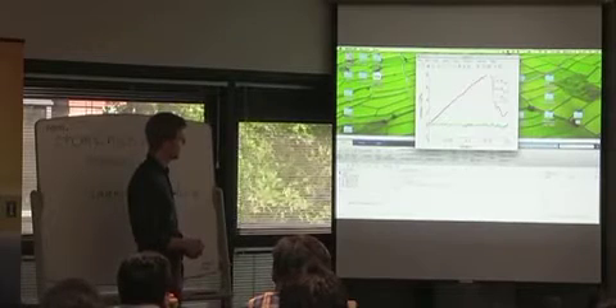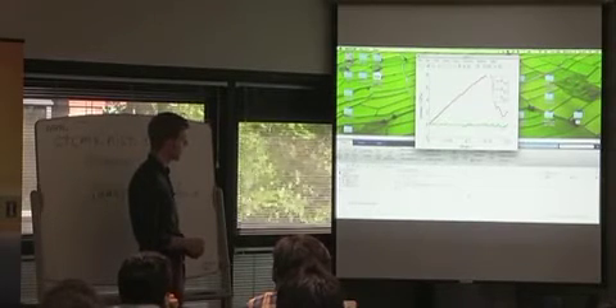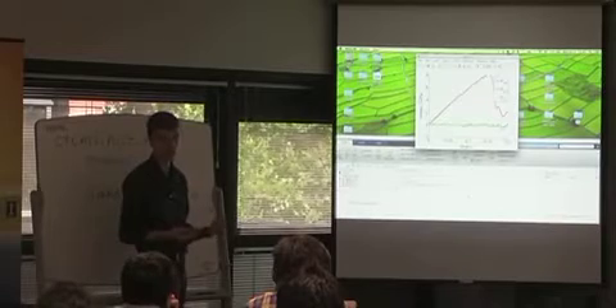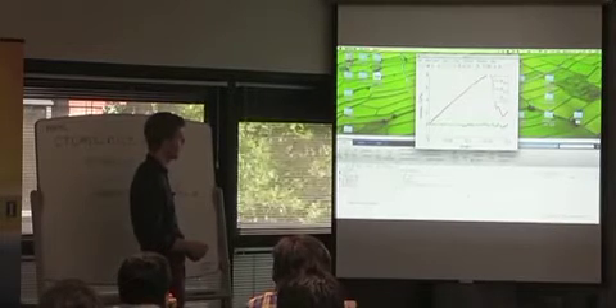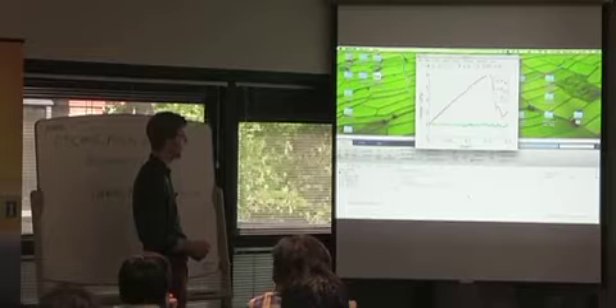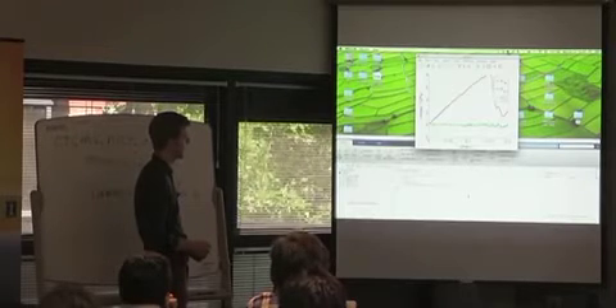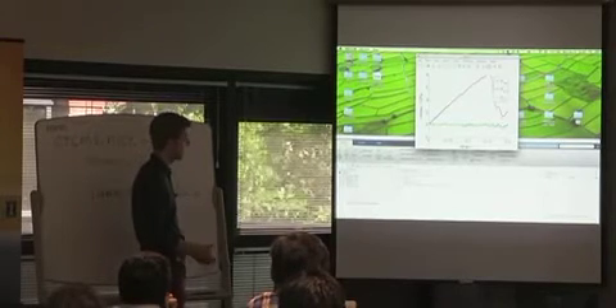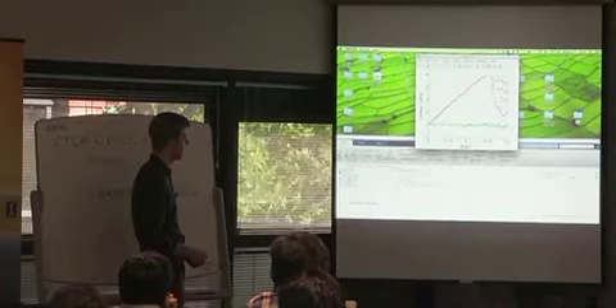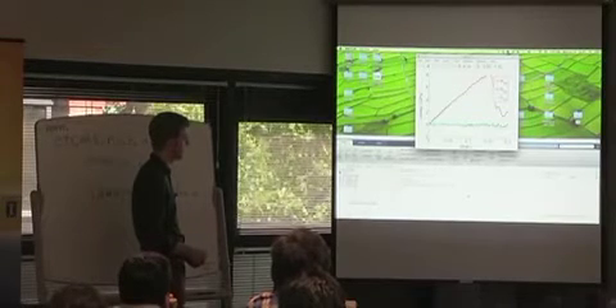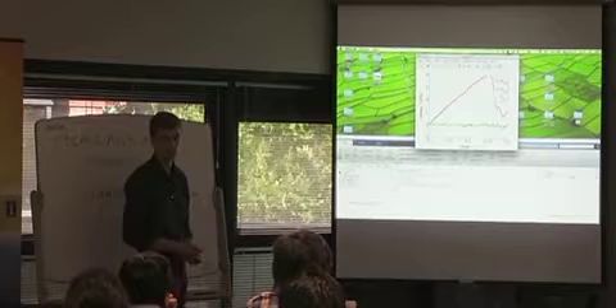And so like we said at the beginning, the Young's modulus is the slope of this line. I wrote a little routine into the M file that's going to do a linear regression on the first part of this curve, between 0 and 0.05 strain, and compute the gradient of this best linear fit, which is the Young's modulus in gigapascals. The Young's modulus came out as 62.69, and these are the confidence intervals on that.